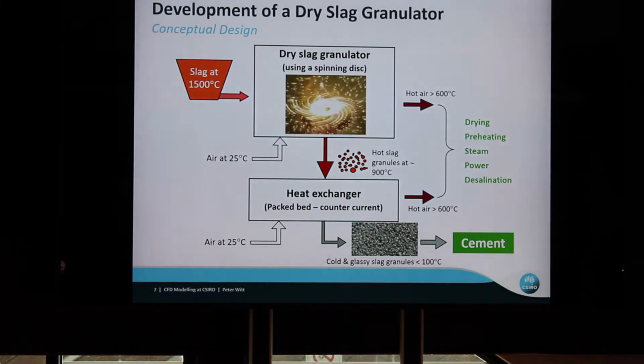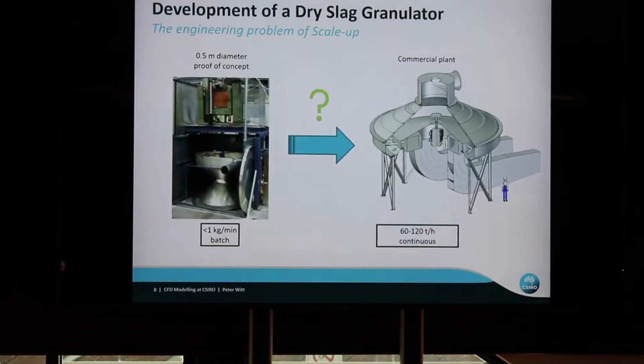CSIRO had a concept that if you drop the molten slag onto a spinning disc, you could produce droplets. If your slag came in at 1500 degrees, you blew air into the system, you could cool those droplets, produce granules of about 2 millimetre size down the bottom that would be crushed up and used in cement, and you might be able to produce reasonably high-grade heat. So that was the concept.